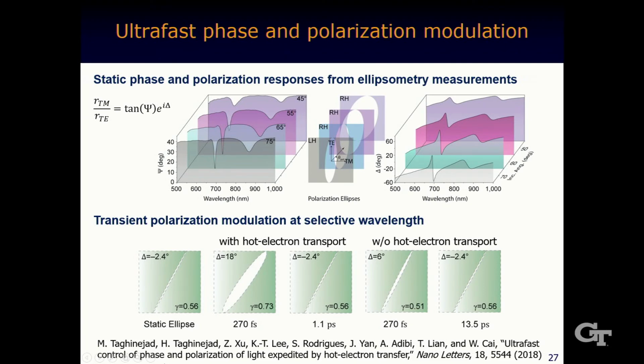And other than the intensity modulation, the hot electron dynamics can also help us to enable polarization and phase modulation of light, because you know phase is related to the refractive index. Similar to the conventional optical Kerr effect, we can use metal along with hot electron transport to modify that. Let me just show you one selective result. Without hot electron generation, basically its output is a linearly polarized light. With hot electron transport, within about 200 femtoseconds, the polarization of light is modified substantially, and within about 1 picosecond, it goes back to the initial status.